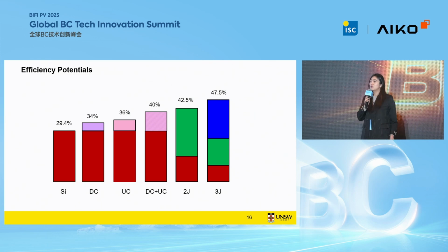But for the 2-junction, the 3-junction, or the multi-junction devices, we actually rely a lot on the top subcells. And the silicon, which is the red part, only contributes a small portion of the overall efficiency. So here I just want to say the down conversion and up conversion is really an elegant way that we can further push the efficiency limits, and also get the full potential of silicon devices. And we are not competing with Tandem, because you can apply these layers on Tandem as well.